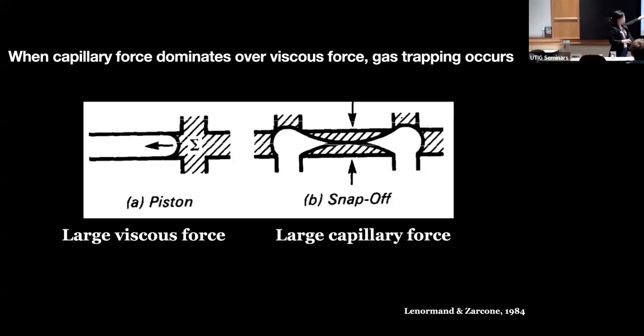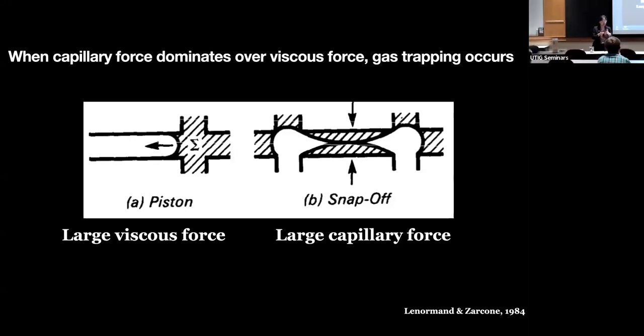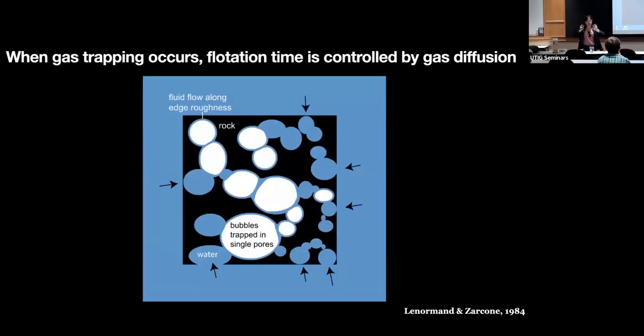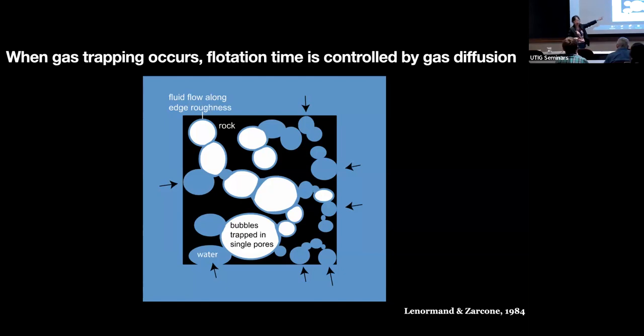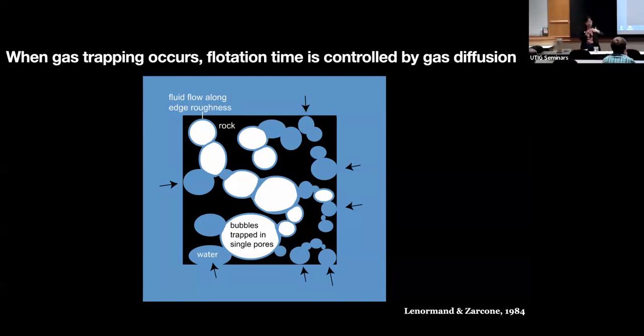The basic point is, if you have a large viscous force and a pore you are trying to go into, the liquid is just going to flood in like this, okay? But when you have a large capillary force, the liquid is not going to flood into the pores. Instead, it's going to go around the edges. It's going to fill all the edges. In the end, you can see these bubbles being trapped in these pores, okay? But the infiltration theory still works. It just only fills the edges instead.